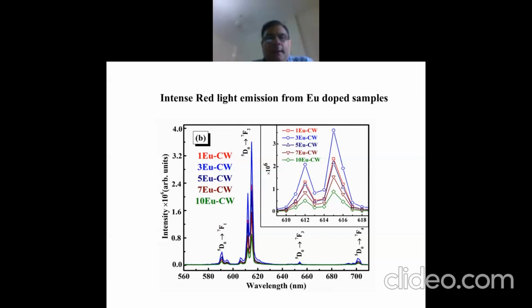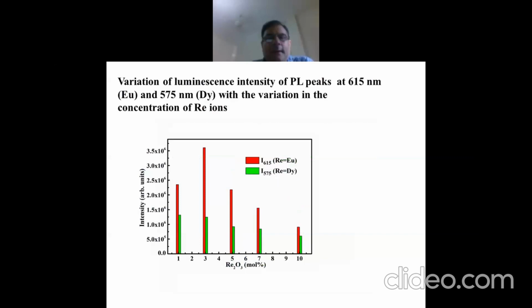So europium emits very strongly in the red part of the electromagnetic spectrum. So you can get red phosphors by doping with europium oxide. And this curve tells you how the intensity of photoluminescence of europium line at 615 nanometer varies with rare earth oxide concentration. Intensity for europium oxide is maximum at 3 mole%, and with dysprosium